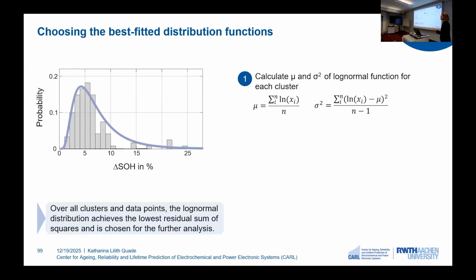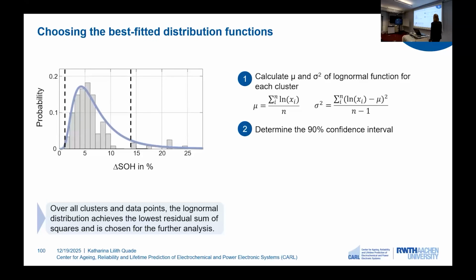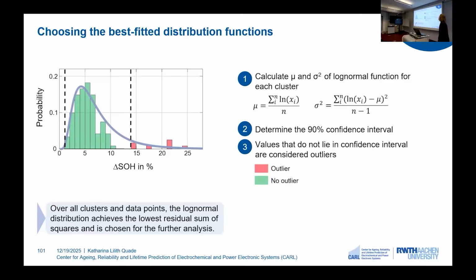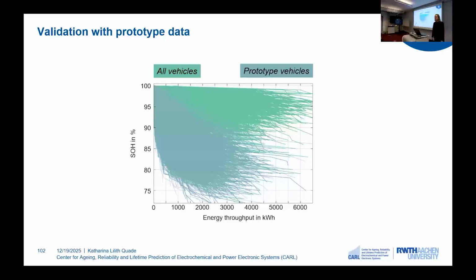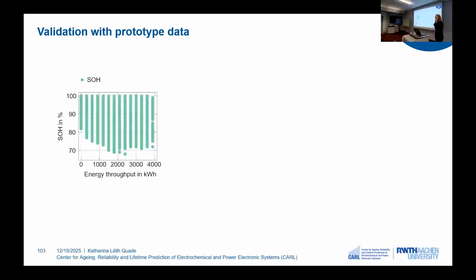And now we have different steps to detect our anomalies. First, we calculate the characteristics of the log normal function for each cluster. We determine the 90% confidence interval, and then we say that we have outliers here in red, for example, when they lie outside of our confidence interval. We also want to validate our data. And we were very lucky that we had prototype data. And this prototype data is visible here in dark green. We can see that for these vehicles, the SOH was consistently underestimated. And now we want to see whether and how much of these data we can detect.